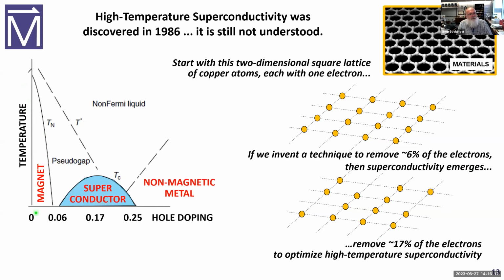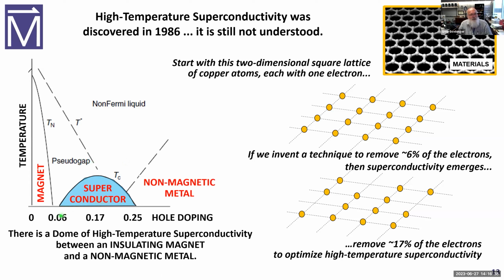And we can create a phase diagram of temperature versus hole doping, which is just a fancy term for how many electrons we are removing, because it leaves behind a hole. So as you get to 6% holes, you get the superconducting phase. It's optimized at 17%. And these three phases that are in red, we understand. The two in black, we're still trying to figure out. But you've got a dome of high temperature superconductivity that's between an insulating magnet and a non-magnetic metal.